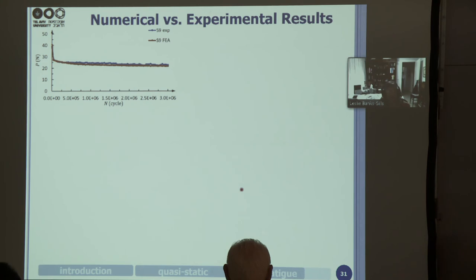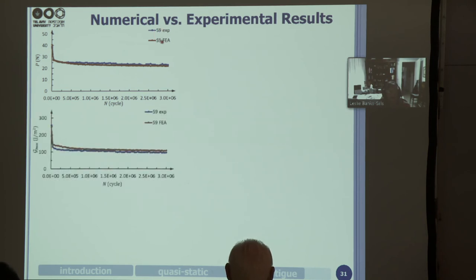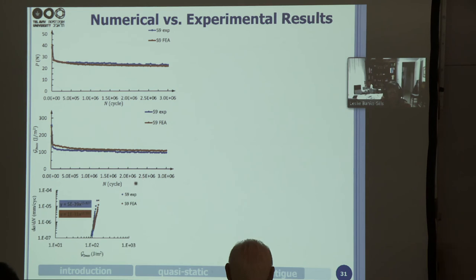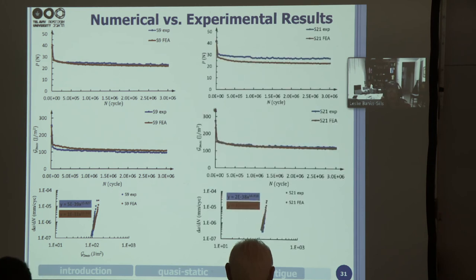So now, if we compare the experimental results to the finite element results, and this is Pmax as a function of n, we have very good correlation for specimen S9. And we compare G1 max versus n. And here is our da/dN versus G1 max curves. These are the specimens that went 3 million cycles, and we have another set, and we get relatively good correlation between the numerical and the experimental results.